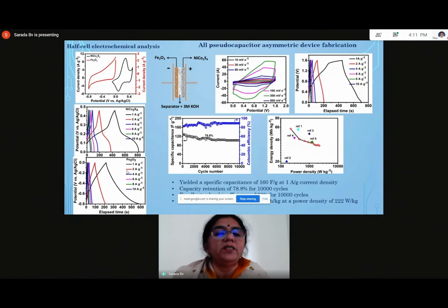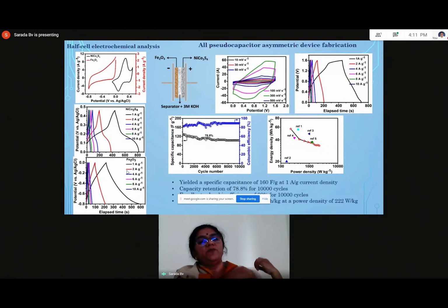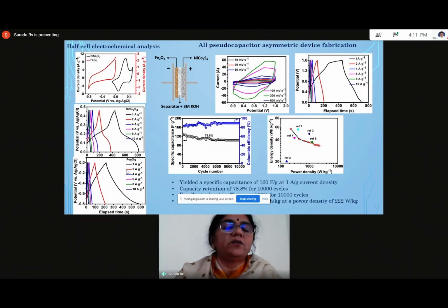oxide phases are formed. And the advantage of using these metal oxide based electrodes on both the sides is that first it increases the potential window, and through the potential window it has very high output. And as you can see over here from the cyclic voltammetric behavior of the pseudocapacitor, and you can see over here the charge discharge curves, and also it has retained 78% after 10,000 cycles. And this is a very good output that we have achieved, and this is going to be a breakthrough for the pseudocapacitors with very high energy. This is expected to achieve very high energy density and a wide potential window. And throughout the potential window, it gives a very good